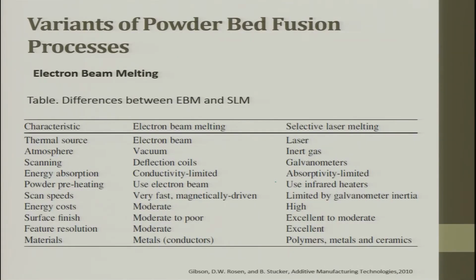So, these are the summarizing things: thermal source, electron beam versus laser beam. Atmosphere, you have vacuum versus inert gas. Scanning, it is a deflection coil. So, in EBM we use a deflection coil, here we use a galvo, because the galvo is used to give the information on the XY plane. Then energy absorption is conductive, here it is absorptivity. These two properties are completely different. This is an optic based property.